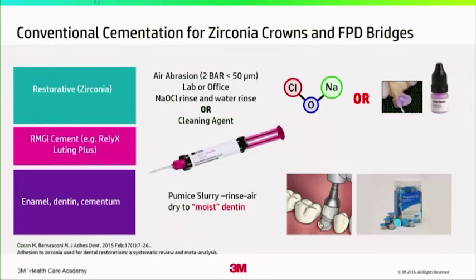My choice for resin-modified glass ionomer cement, there are two or three of them out there. I've used the RelyX Luting Plus for the simple reason, the high reliability factor, of course. But the other reason I do like it is because I can use my light to get a gel set and peel it away from the margins while I wait for the cement itself to eventually cure in its auto-cure mode. So I find it very convenient.